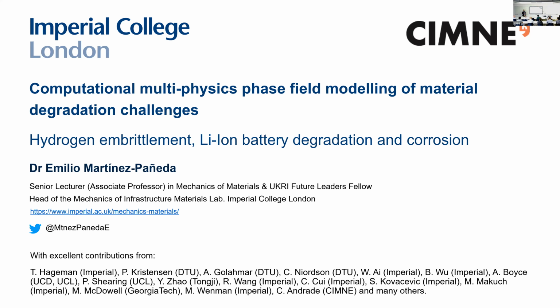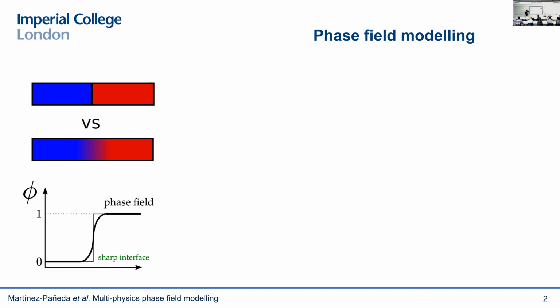Before I start, something that is common to all of these problems is these phase field methods that I'll be talking about in detail today. So let me just briefly introduce them to start with. The idea is computationally quite simple. Instead of having a sharp and discontinuous interface, you can smear that interface over a finite domain and then use an auxiliary variable, the phase field, to describe where the interface lies. The phase field will take a distinct value in each of the phases, like a 0 in the blue phase and 1 in the red phase, and then it will vary smoothly in between. And then you just need to define a differential equation for the evolution of this interface, for the evolution of the phase field, and you're able to simulate interfacial problems of arbitrary complexity.